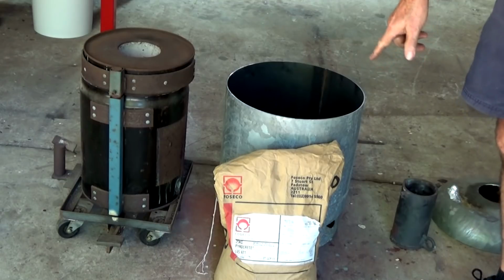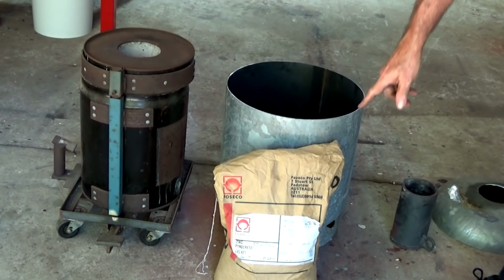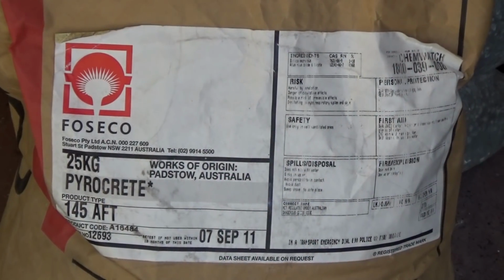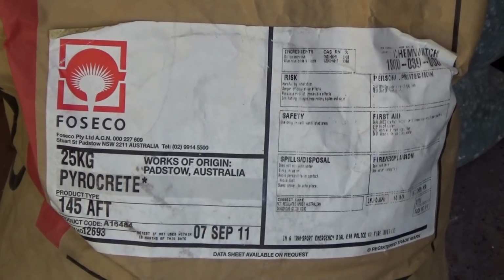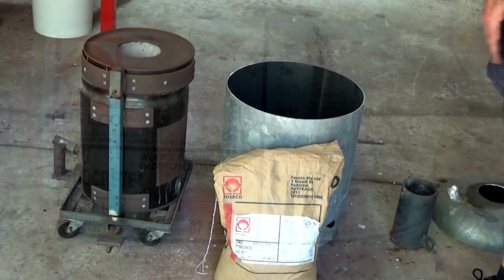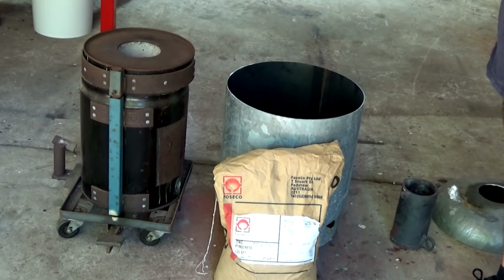Okay, this is pyrocrete. This one is 145. Now, this is supposed to be good to about 1400 degrees centigrade, or a little bit more. On my old furnace, it stood up to that sort of use on a regular basis. Never really took it to 1400 degrees C, probably to about 900, and it's been absolutely perfect. Nothing is cracked or broken or fallen away. The coating on the inside still looks good.